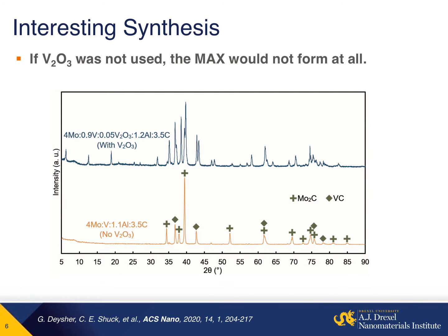Moreover, we saw something very interesting with this synthesis. If we didn't use vanadium oxide, we used V2O3 in our case, for the synthesis, just in small amounts, we wouldn't form the MAX phase at all. Instead, we formed bulk carbides, which wouldn't be useful for the study of MXenes. Now, what this means is there's some kind of simultaneous aluminothermal reduction reaction occurring during our high temperature annealing process, and this is something we're studying more in depth to understand why this is necessary.